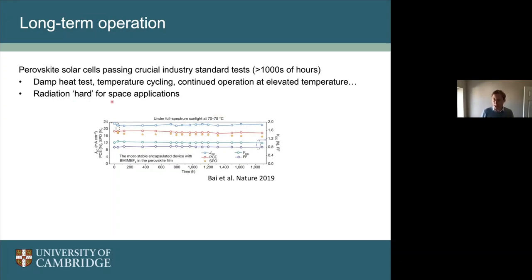And we've also been doing a lot of measurements testing their radiation hardness for space. So we bombard these cells with high energy protons to see if they survive, and they do. These perovskite materials are actually very stable and tolerant to a lot of this high energy radiation, which is very promising for space applications.